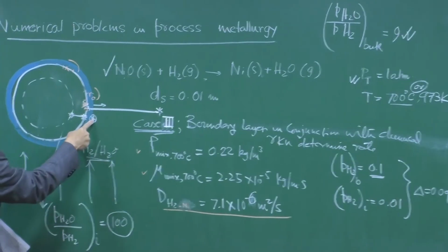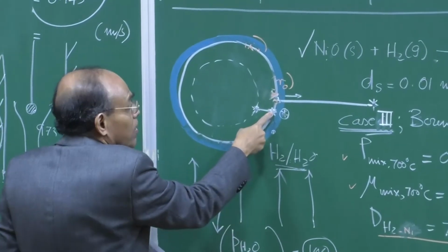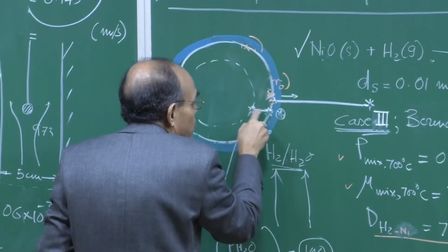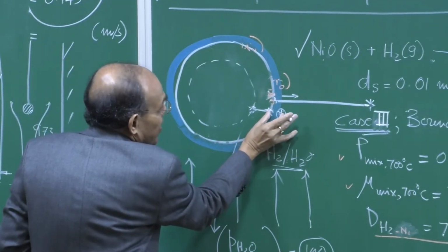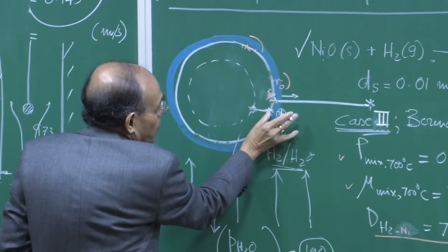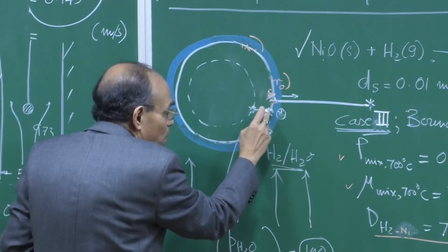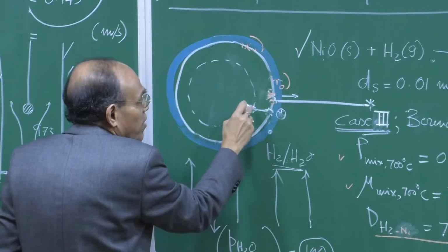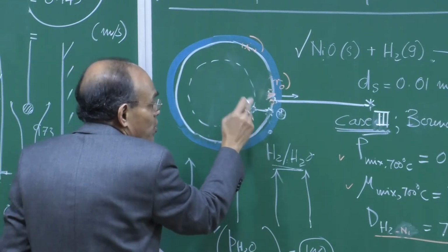This concentration is known as the bulk concentration, but this concentration, as I have said, because diffusion is not there, we will have this concentration and this concentration identical. So, this concentration differential drives the boundary layer mass transfer process with this particular surface concentration being unknown. Similarly, this concentration drives the chemical reaction process and this concentration is not known.